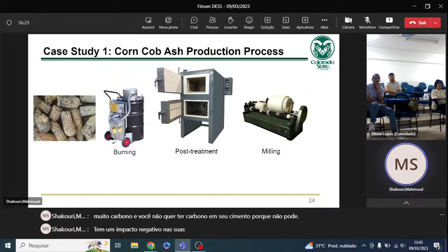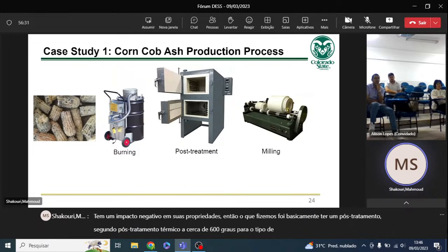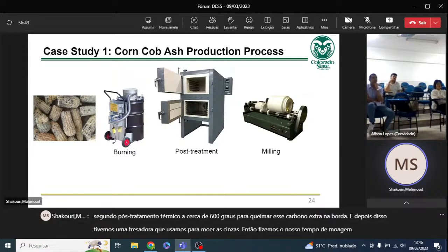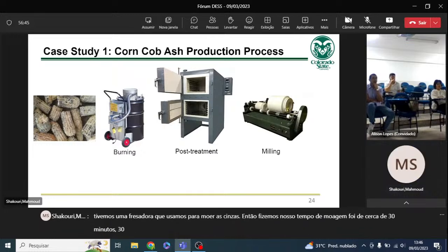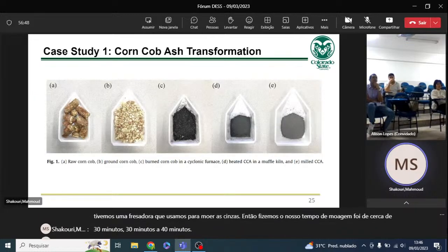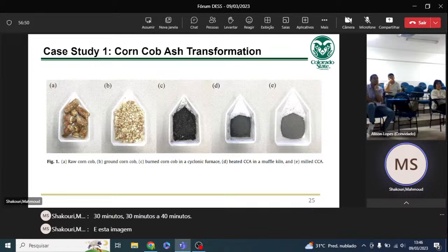So what we did was basically we had a second heat post-treatment at about 600 degrees to burn that extra carbon in the ash. And after that, we had a milling machine that we used for grinding the ashes. Our milling time was about 30 minutes to 40 minutes. And this picture shows the pictures taken at each step showing the final products that we had.